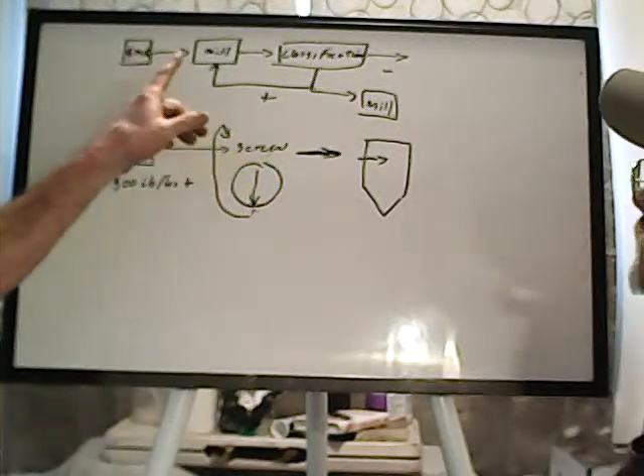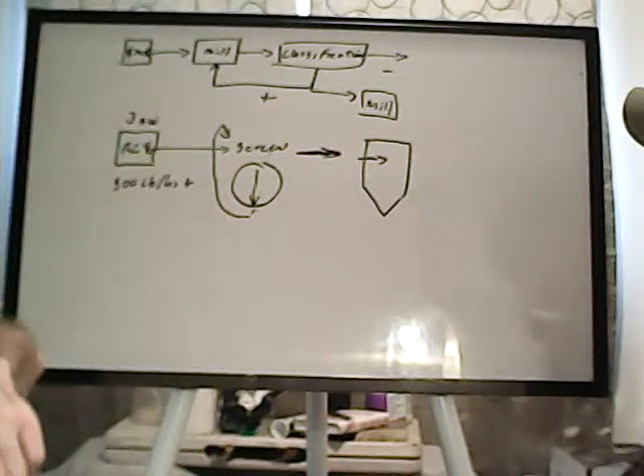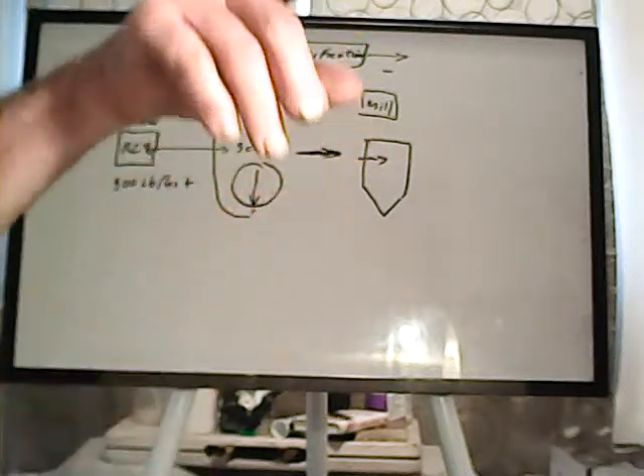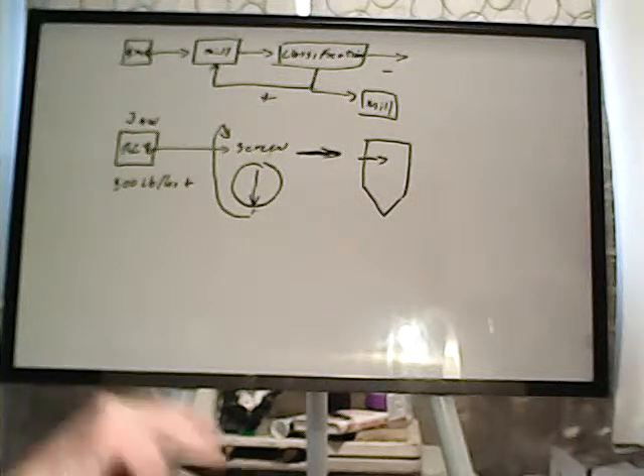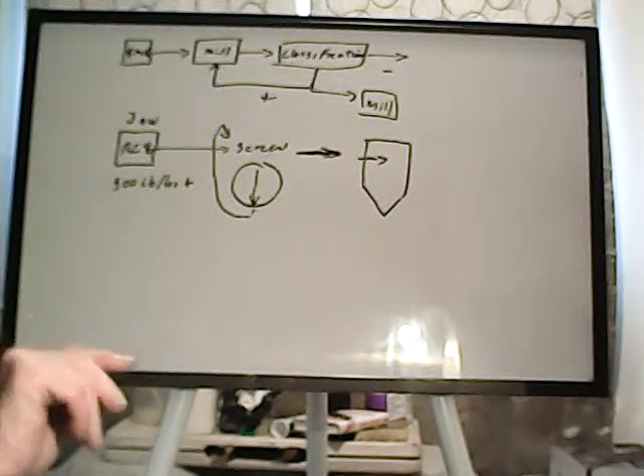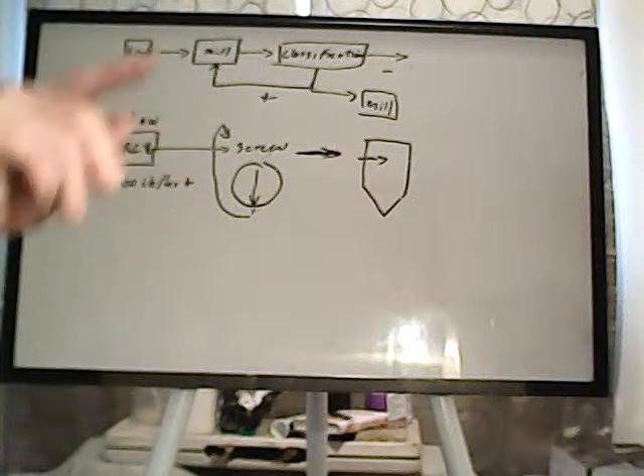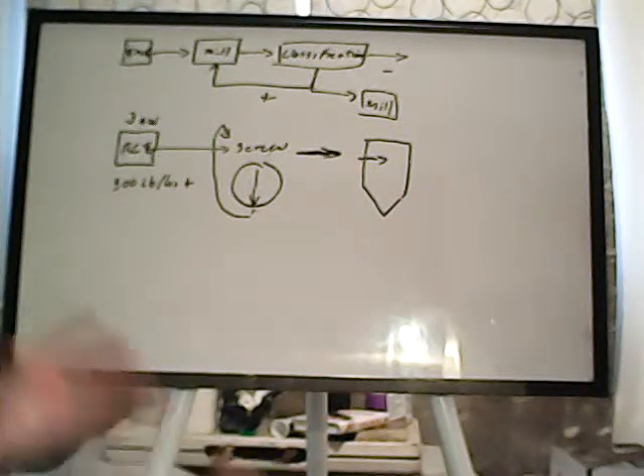But anyhow, so this is what I'm doing right now to try and figure it out. I've done assays. I screened it. I've done the bottle. Well, not completed the bottle because the coarse stuff you're working on. I've still got digesting. I did samples at 24 hours for all three, samples at 48 hours for the two coarser fractions, and then I'm going to get a sample at 96 hours for the 35 mesh plus, because of course it's going to be slower.